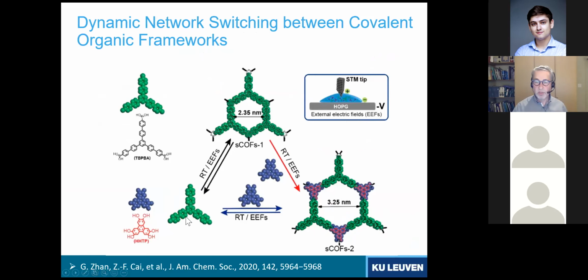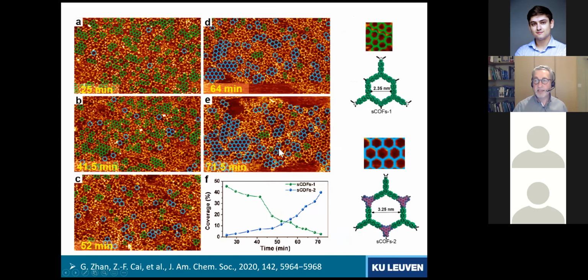So starting from the monomer self-assembly to the monocomponent 2D covalent organic framework of the boronic acid, the one I have shown you before, by then applying the electric field, we could go to the bicomponent covalent organic framework, and we could realize the polymerization as well as the depolymerization of this process. So we call this dynamic network switching because we can convert one covalent organic framework into another covalent organic framework. Again, these frameworks are only one molecule thick, and they are supported by a graphite substrate.